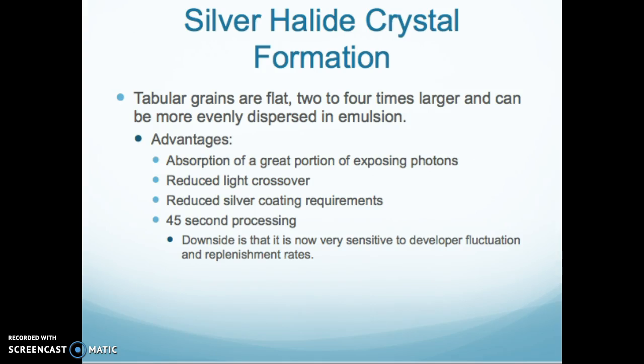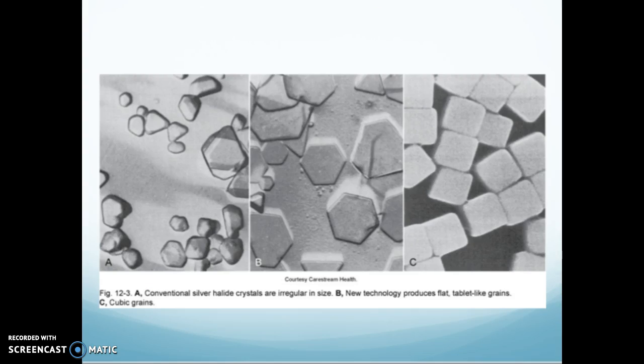Tabular grains are flat, 2 to 4 times larger, and can be more evenly dispersed in the emulsion. The shape of these crystals is really important. The advantages of this shape of crystal are absorption of a greater proportion of exposed photons, which is big, reduced light crossover, which we talked about already, reduced silver coating requirements, and 45-second processing. The downside is that it's now really sensitive to developer and replenishment rates. When we talk about the processor, you'll understand that a little better. It'll come together. Here are the different shapes of the crystals.